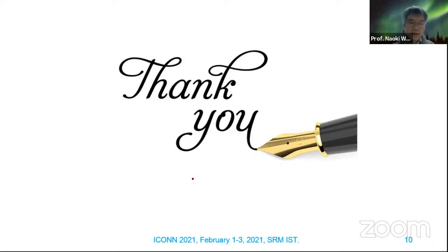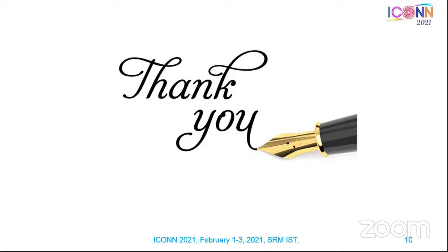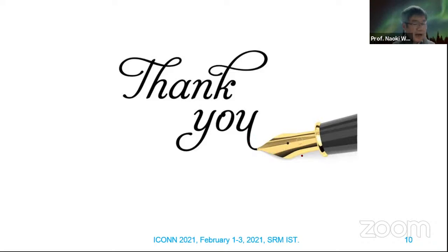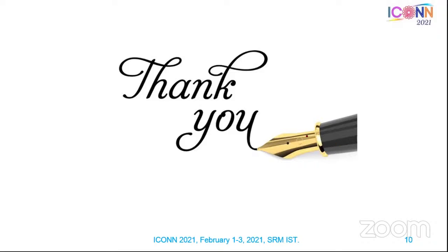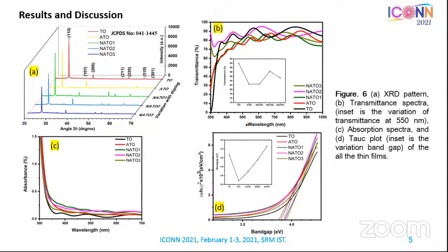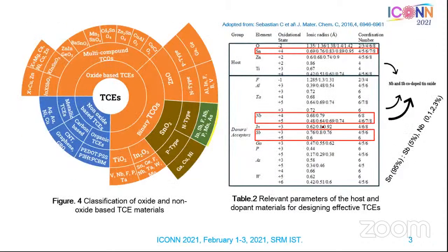And why do you want to carry out co-doping? I mean, single doping, maybe only antimony or only niobium. Yes, sir. My senior had doped antimony, and he got a lower transmittance than after doping with niobium. So that's why we went for niobium co-doping. It is increasing the transparency, which helps form the crystallites more clearly.